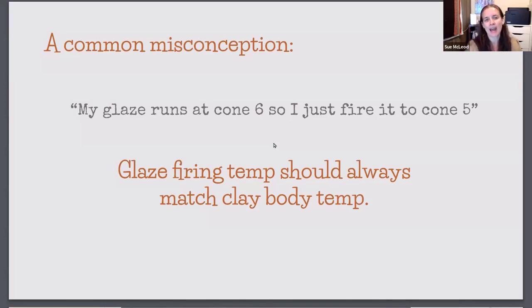So your clay body, as temperature goes up, when we bisque fire our clay body, it becomes very porous, which helps with the glazing process. And then as the temperature increases in the glaze firing, those pores get filled in with melted silica. Your pottery shrinks in the glaze firing. And we want our pots, especially at stoneware temperatures, porcelain, stoneware, cone 6 and above, we want vitrification. So we don't want to underfire our clay body just because our glaze is running at cone 6.